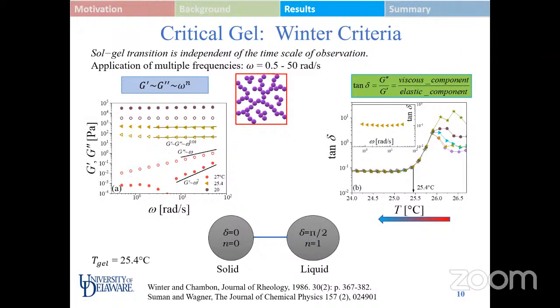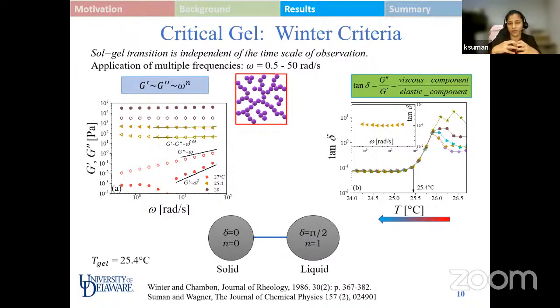Yeah, it does, I think. So you're saying probably wouldn't be observed because it wouldn't behave like an adhesive hard sphere system. Yeah, and it won't be that arrested that it undergoes phase separation, forming colloid-rich and colloid-lean phases in case of depletion gels, because ultimately it's very viscoelastic in nature. As we saw, even after the drop in viscous modulus value, it saturates to a high value of modulus. It's not like going to a very low value of modulus. So it needs to have a firm elastic network, which gives rise to such viscoelastic nature of the gels. So I believe this will be absent in depletion gels, although you can try and let me know.